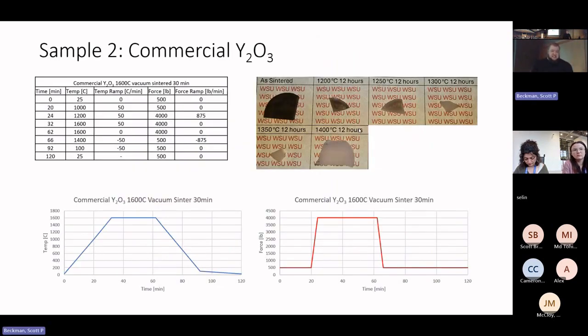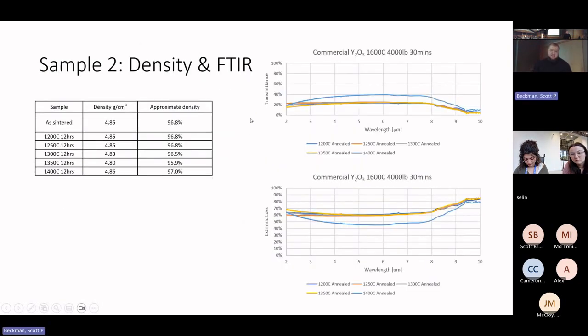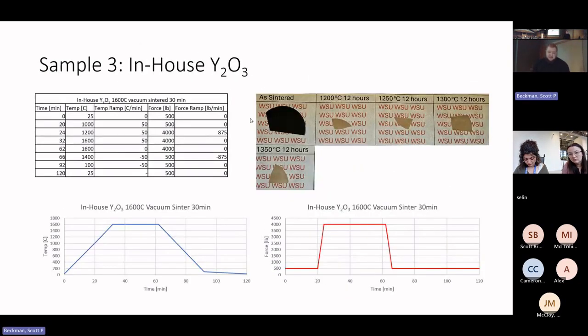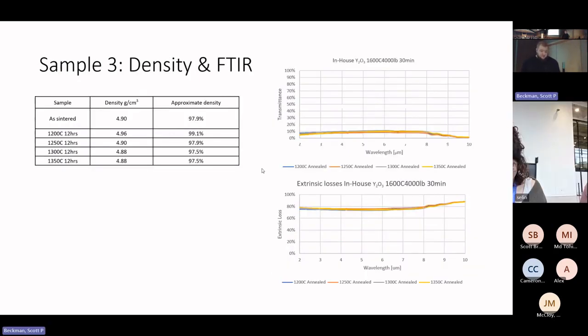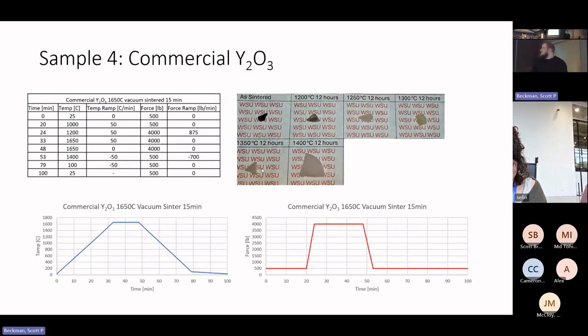So here we can go through several other samples we found. These pellets were sintered at the same temperature, 1600 degrees C, but for a longer time of 30 minutes. And we can actually see that we're starting to get some light through the pellets. It's a little bit hard to see in this top left as-sintered image, but in the real pellet you're actually able to see some transmittance through the pellet, and then we get slightly more transmittance as we increase our annealing temperature before seeing a decrease in transmittance once we reach even higher annealing temperatures.